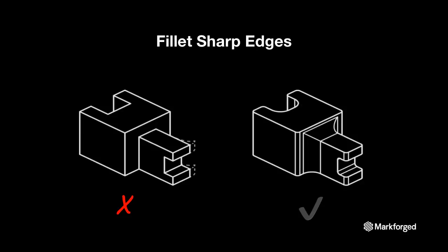And this is really nice because it generates a lot less internal stress. But at the same time, your part is still shrinking down, albeit gently and over a much longer period of time, but it is going to shrink down a little bit. So one of the best things you can do is to avoid stress concentrators like sharp edges. There is a possibility with extremely sharp edges in a part that you may see some deformation during the sintering process. So one way to avoid this is to add gentle fillets.